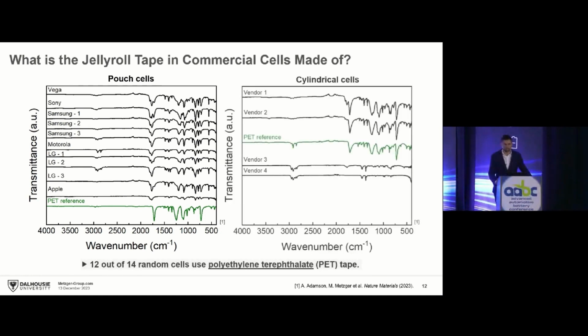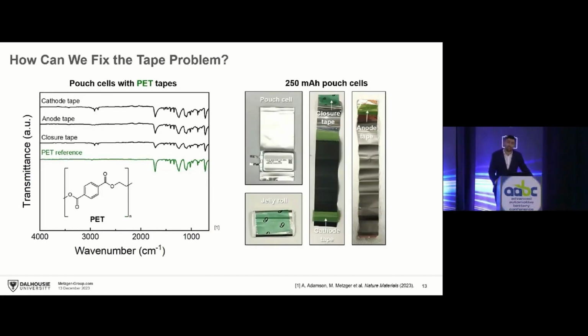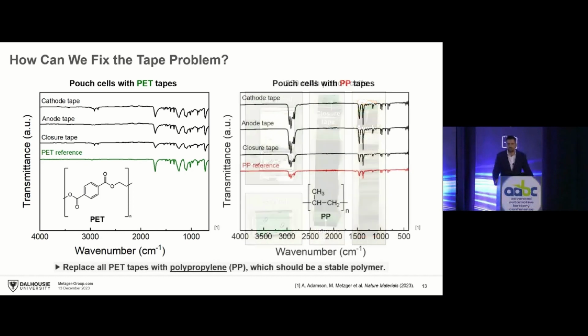Then we looked at some cylindrical cells, also some of them for automotive application. Out of 14 random cells we selected, 12 of them contain PET tape. So how do we fix that problem with the PET tape? In our cells, we found a very simple solution. We just replaced all those tapes that are made from PET with polypropylene tape, PP.